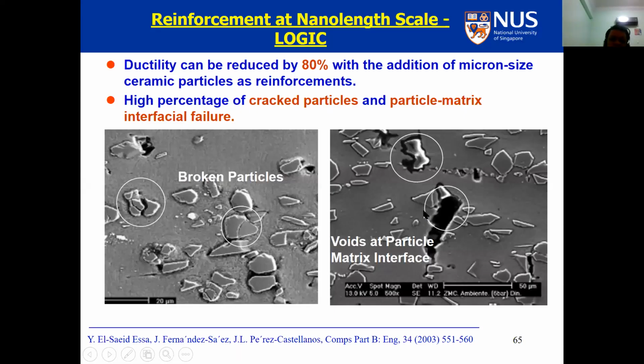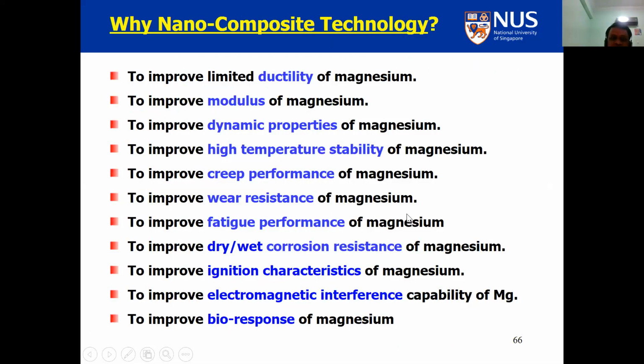Now, why is it important to put in the nano size particle? If you use the micron size particle, for example, they either tend to crack, as you can see in the left-hand side image, or they tend to debond, as you can see in the right-hand side image. Both of these particle damage mechanisms lead to a compromise in the mechanical properties. They are the site of crack nucleation, which will eventually grow and fail your material. Nanoparticles don't do that, and that is why we go for the nanocomposite technology.